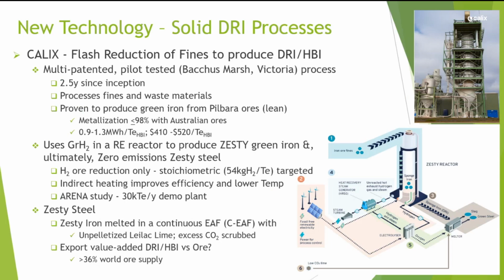Solid DRI process, Calix is a new Australian company that's actually, it says 2.5, but it's 3.5 years now since inception. They've proven the ability to produce green iron from the Pilbara ores. Metallization is anywhere up to 98%, but not with all of the ores yet. They're using green hydrogen in two concentric tubes, basically. Green hydrogen on the inside tube with the countercurrent to the ore fines, and renewable energy in the outside column. They're getting close to stoichiometric hydrogen use. They're doing an ARENA study, or requesting an ARENA study right now, for a 30,000 ton a year plant, where they will actually increase the height of the tubes to give them longer residence time for the more lean ores that will technically reach the 90+% metallization.